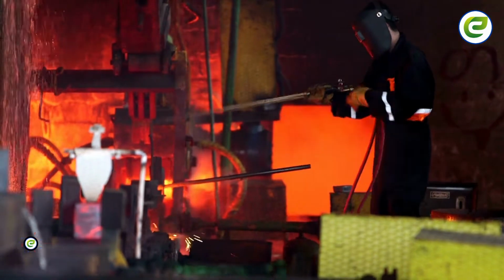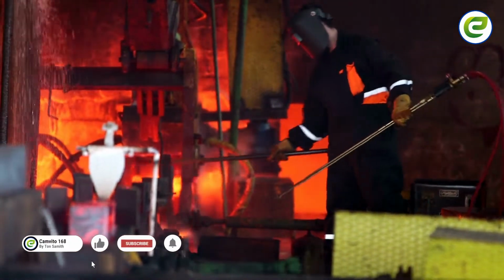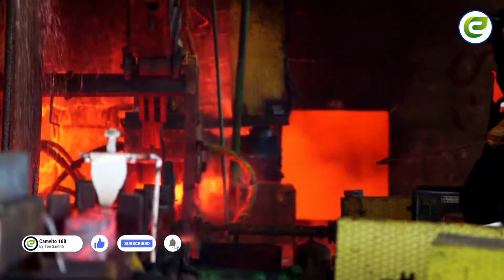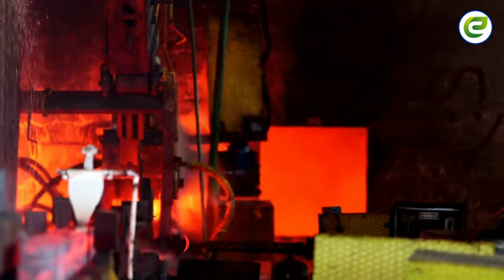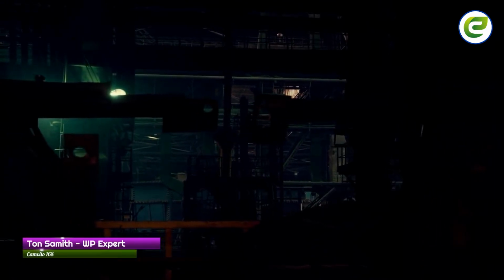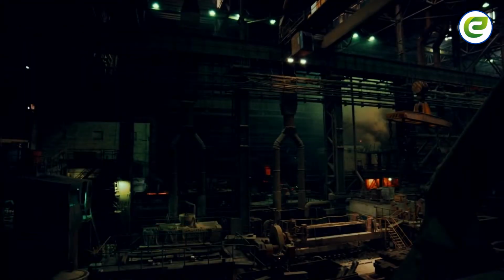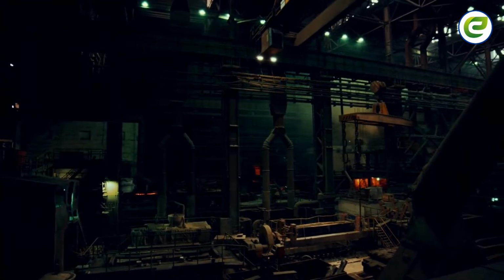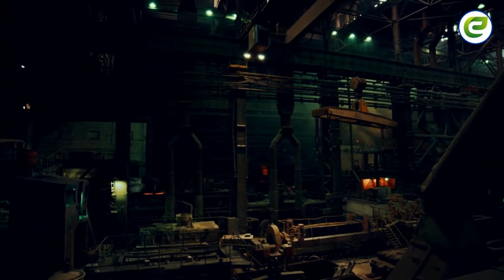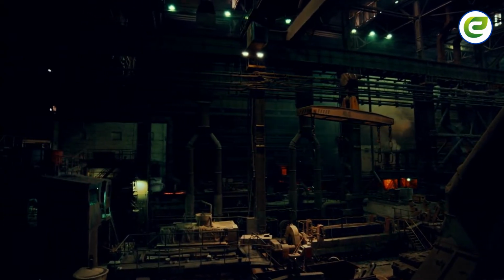The carbon contents of the early irons ranged from very low, 0.07%, to high, 0.8%, the latter constituting a genuine steel. When the carbon content of steel is above 0.3%, the material will become very hard and brittle if it is quenched in water from a temperature of about 850 to 900 degrees Celsius, 1550 to 1650 degrees Fahrenheit.